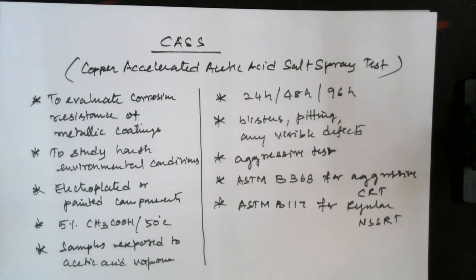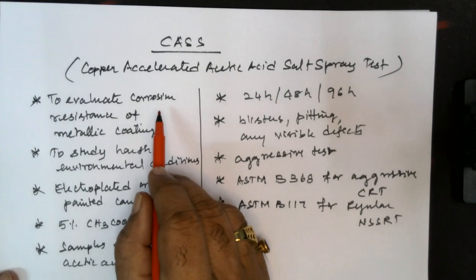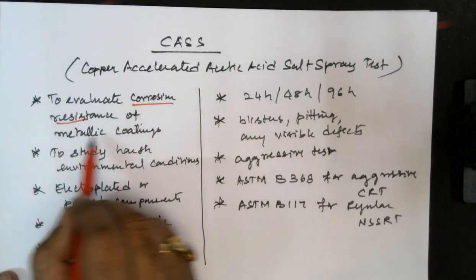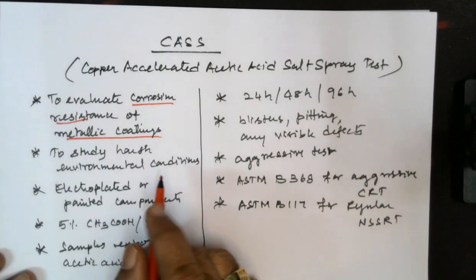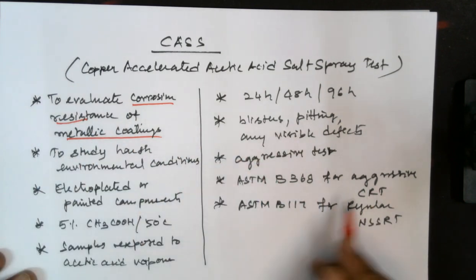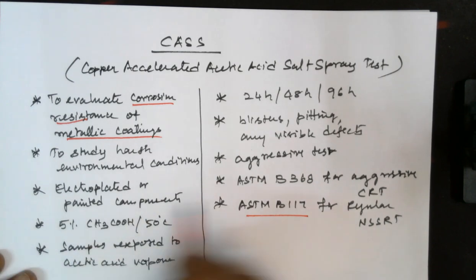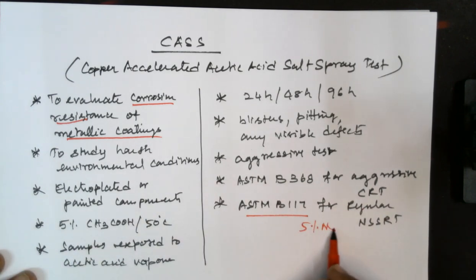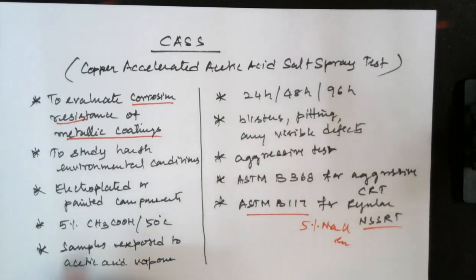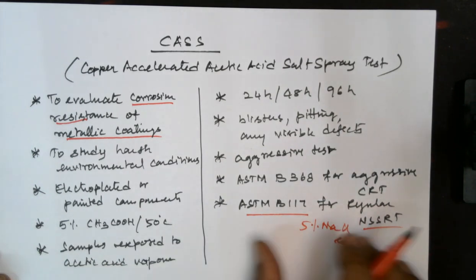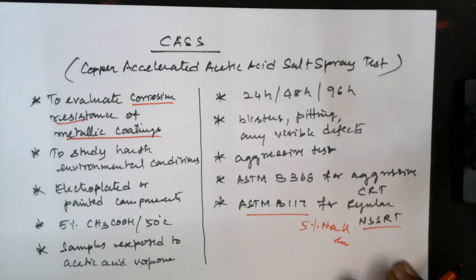CASS, that is copper accelerated acetic acid salt spray tests. This test is very useful to evaluate the corrosion resistance of metallic coatings under stringent conditions. It is different from ASTM B117, which is regularly done with a 5% NaCl solution. That is a neutral salt spray resistance test, a regular salt spray resistance test used for testing corrosion resistance for metallic coatings and electroplating materials.